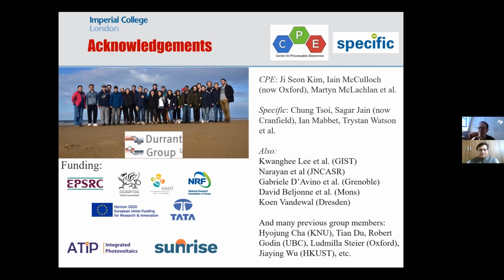So I can see the first question is from Amit Kumar about the difference between inverted and conventional perovskite solar cells. So the directionality of charge extraction from a solar cell depends upon the contacts and the electrodes, on which side is the anode and which side is the cathode. And there's various conventions. And unfortunately, the nomenclature for inverted and conventional is opposite for perovskite and organic solar cells. For an organic solar cell, the transparent contact, which is normally the one at the bottom deposited on the ITO, if that's the hole collection layer, then that's a conventional organic solar cell. And if the bottom contact, the ITO, is the electron collection layer, then that's an inverted solar cell. And it's the opposite for perovskites, which is just unfortunate.